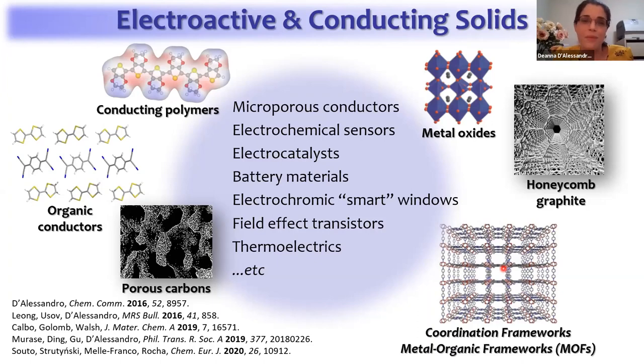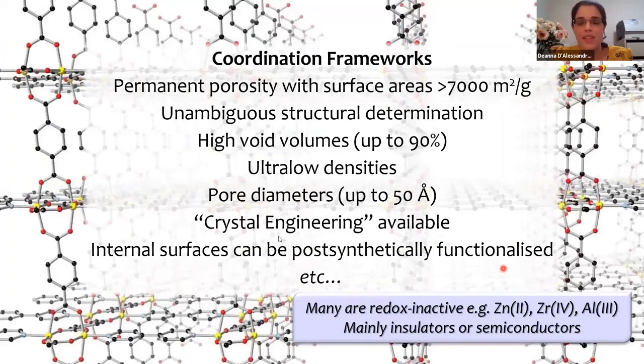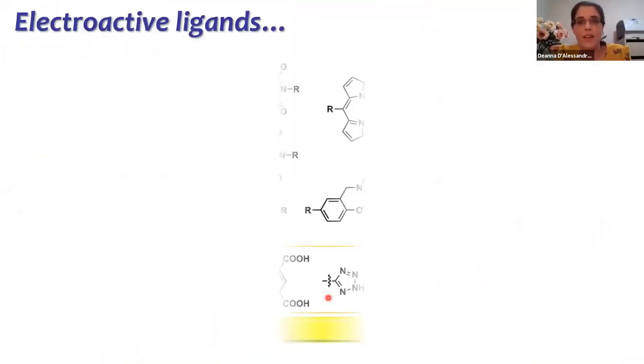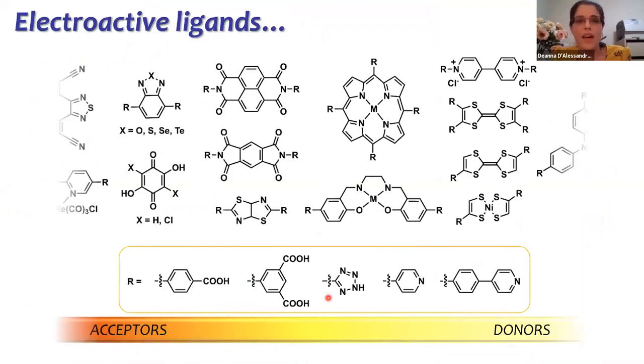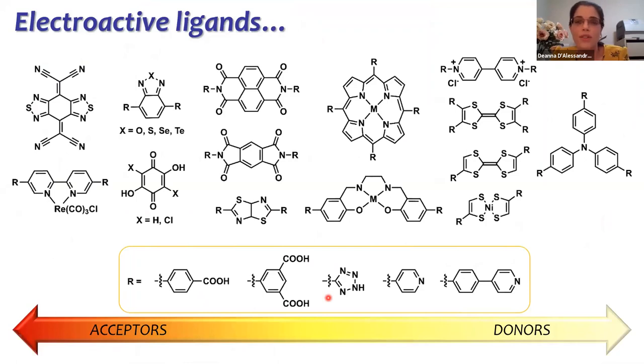And of course, we all know very well the properties of these materials that give them their incredibly high surface areas. But what is quite interesting is that the majority of metal organic frameworks, or many metal organic frameworks, incorporate redox inactive metal centers like zinc, zirconium, aluminium. And so for the most part, they're typically semiconducting or even insulating, and only very, very few are really highly conducting. Although, as Susumu has shown, many inroads have been made into that in very recent years. So one issue we have with electroactivity based on the metal centres is that, of course, we know that coordination compounds and metal ions have a preference for particular geometries in certain redox states.